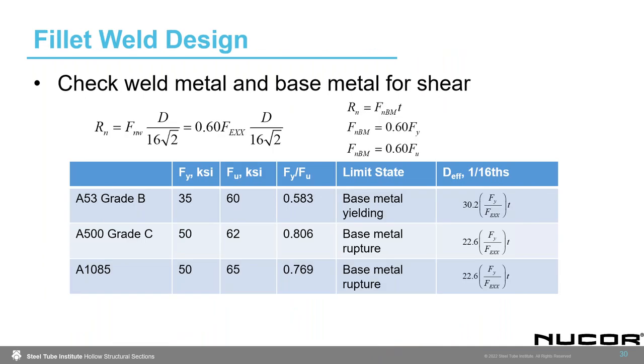When it comes to fillet weld design, there's a table like this. It's in Design Guide 24 and is updated in the newer version of this, but we also need to check the weld metal and the base metal for shear when we're welding to HSS. A500, all the material out there in the marketplace, is all grade C or dual graded B/C. So this table is much easier, especially if you consider just ignoring A53, which I hope everybody is not using for their design. So if we just look at A500 grade C or 1085, depending on which one you're using, you know that base metal rupture is always going to control. So it simplifies our weld design going forward, which is nice.